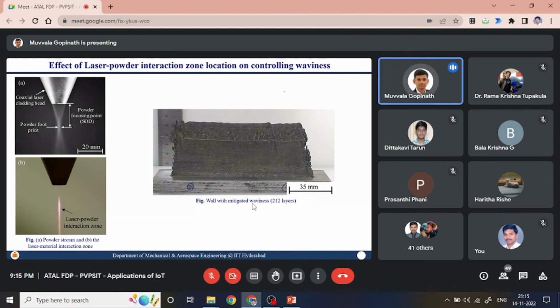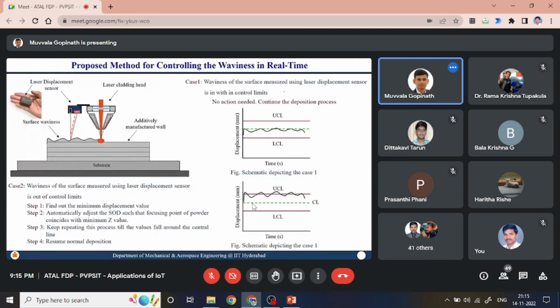So from 40 layers to 80 layers to 212 layers, we are able to control the waviness due to heat accumulation and the waviness due to anomalies like oxidation or something else. Now, if you want to do it in real-time control, because whatever we have done in the previous case, we are monitoring the process and human interference is done, meaning we are intervening in between and changing the process parameters. But if you want to make it automated, you just attach a displacement sensor like this.